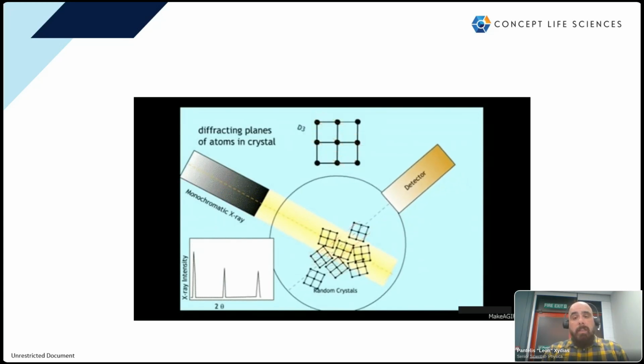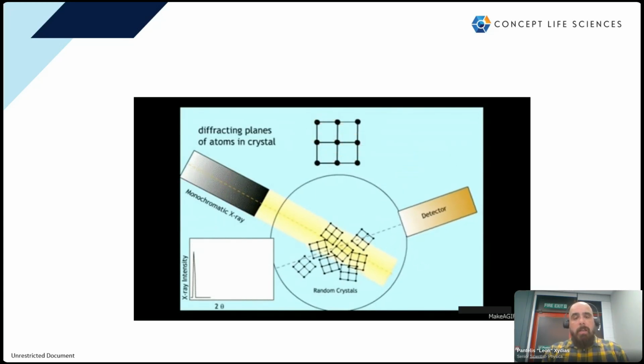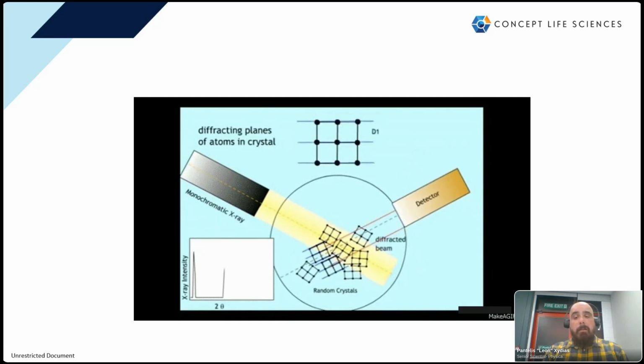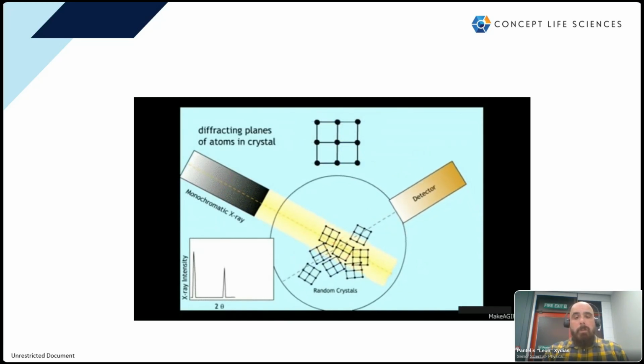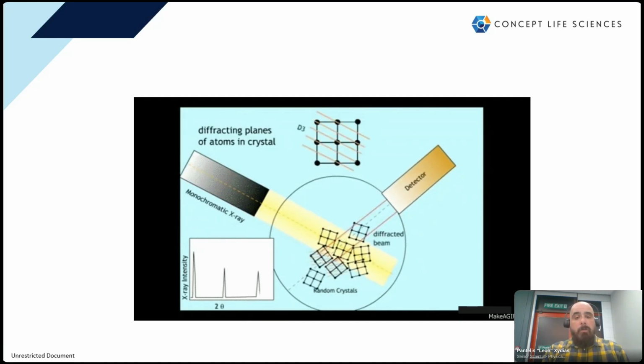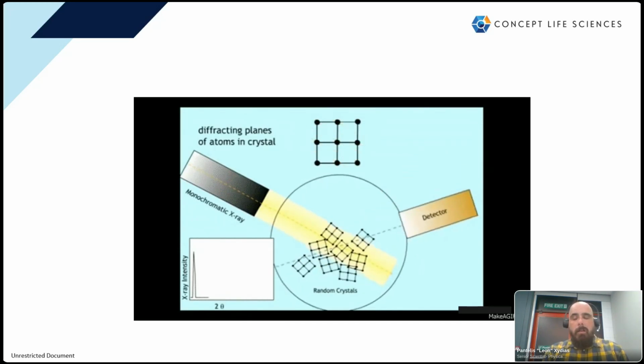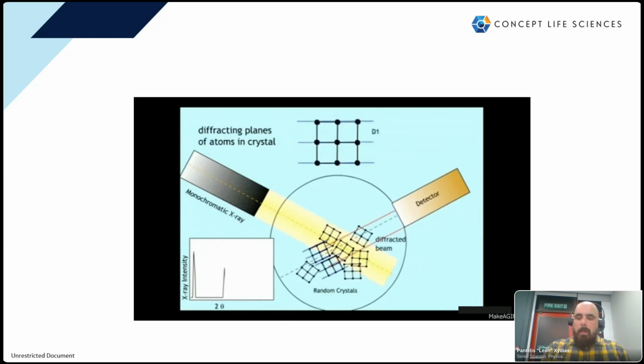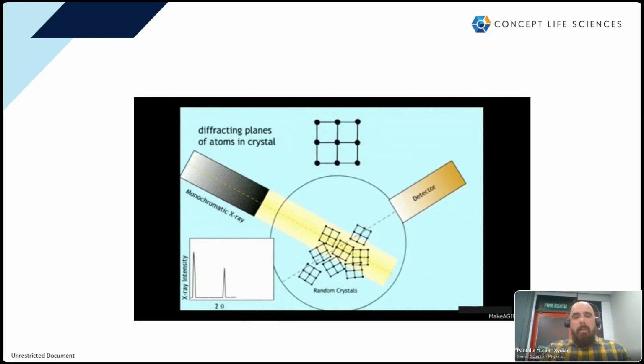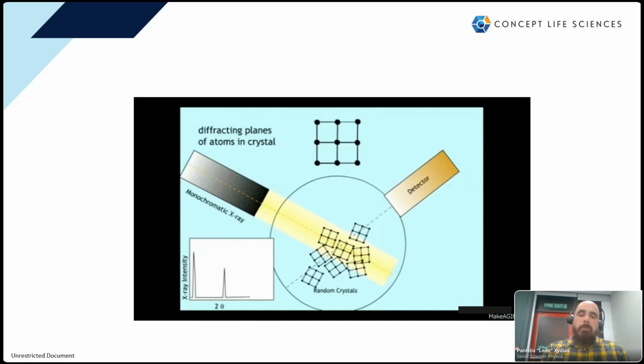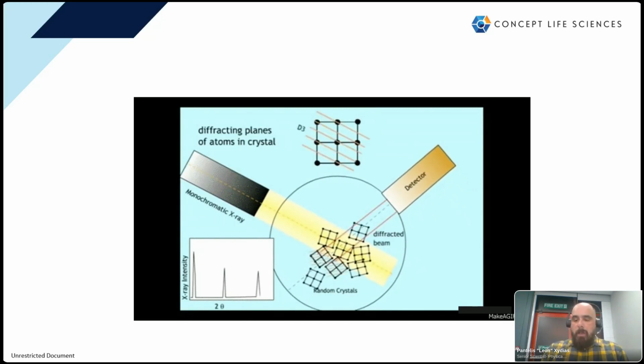And in order to get a representative sample and mitigate effects like preferential orientation or effects from different packing, etc., we usually tend to rotate the sample while the arms of the instrument are also rotating at the angles.